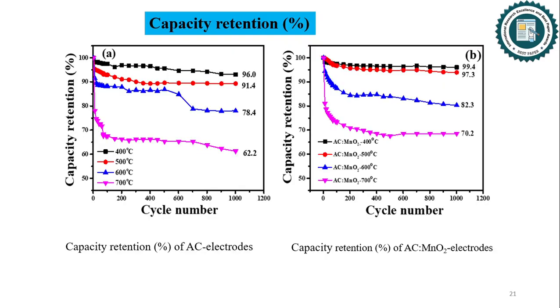The stability of the electrodes was investigated by percentage retention capacity. Long life cycle is one of the vibrant characteristics that an ideal supercapacitor should have. So as can be seen, capacity retention over 1000 charge-discharge cycles at 3 ampere per gram was monitored for activated carbon electrodes and hybrid composite electrodes. All electrodes exhibited an initial stabilization phase followed by gradual decline in specific capacitance after approximately 200 cycles, attributed to material decomposition into the electrolyte during repeated cycling.